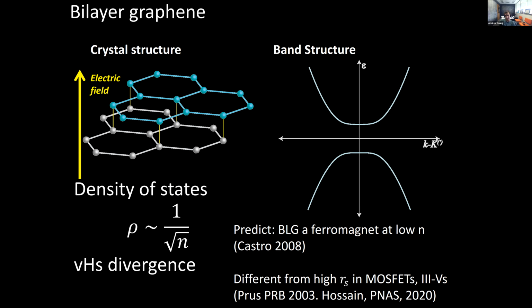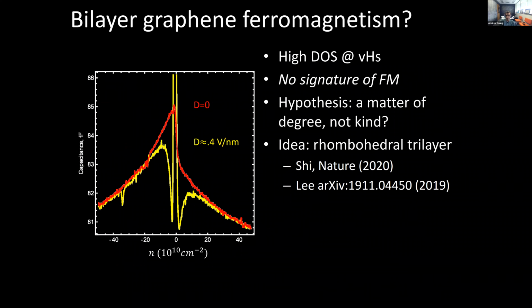And in fact, shortly after the first experimental isolation of bilayer graphene, it was predicted that if you dope it to low densities, close to this Van Hove singularity, you should get indeed ferromagnetism, and there have even been theoretical claims that it should be a superconductor of various types. And actually, we looked for this, 5 years ago or so, and we didn't really see anything.